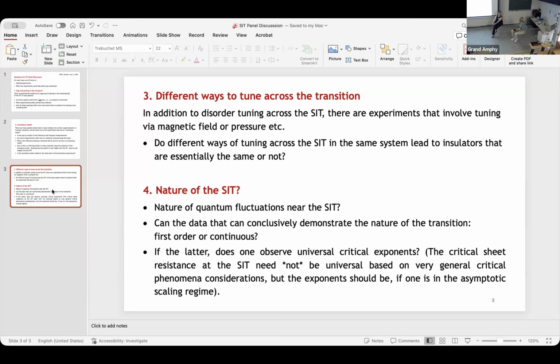Which is that in classical critical phenomena, it is very well known that if you have a first order phase transition, then the presence of disorder actually makes it continuous. Yes, which is the argument. And this is extremely well established by the work of John Hardy and others. Yes. Now, I do know of one example where this might actually be true in a superconductor insulator transition. It's not a particularly well understood example, but experimentally very well studied. So if you underdope cuprates, there's work from Tom Lemberger, and there is work from Bonn and Hardy.